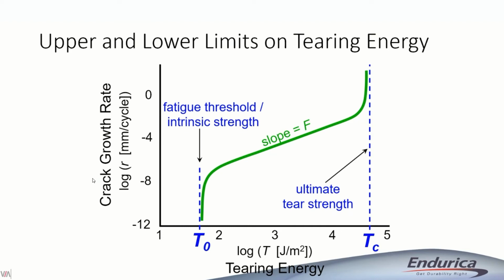So for natural rubber, it's very common to see numbers like F equals 2. For synthetics, like SBR, you might see values like F equals 4. So that's the common behavior. Now, when we're talking about infinite life, we're really going to mostly be concerned with T naught and where am I with respect to T naught? Am I below? Am I above? If I am below, what's the margin that I have?